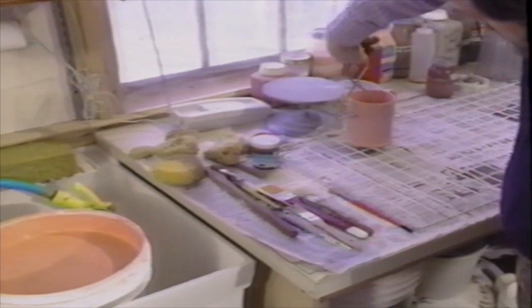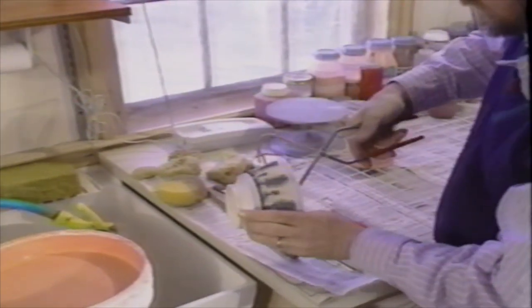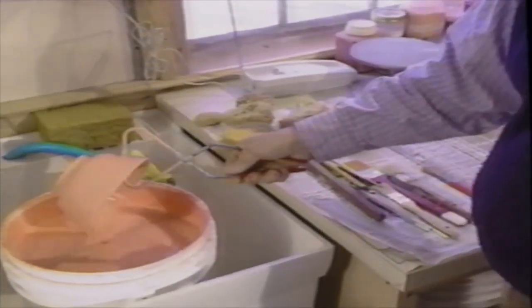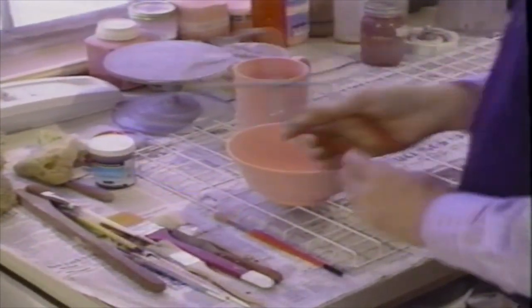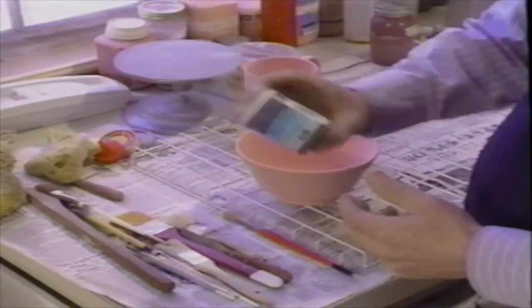After dipping in the glaze, these biscuit-fired shell-edged wares usually had either blue or green oxides brushed into the glaze at the rims. The original potters often used bare hands to dip the wares into the lead glaze, often leaving fingerprints which remain on the finished objects. The water in the glaze is quickly absorbed by the biscuit body, fixing the glaze, which allows the ware to be set down right away. An ornamental green glaze is added to the rouletted band on the mug and to the handle terminals too.